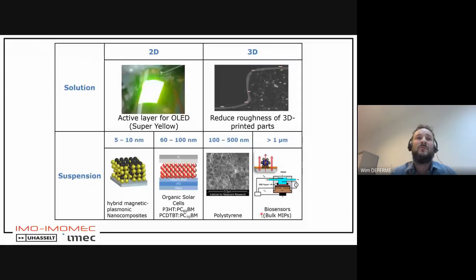The next thing I would like to focus on now is going to nanoparticles, and you see we can deposit nanoparticles going from 5 to 10 nanometers up to more than 1 micrometer. We tried particles having a size of a few micrometers, but then concentration starts to play a big role, because of course if you generate droplets having a diameter of 20 microns, having particles in there of a few micrometers, that becomes already critical. So we can go to 1-2 micrometer in size of the particles, and then a low concentration, but that's, let's say, the limit of the system.